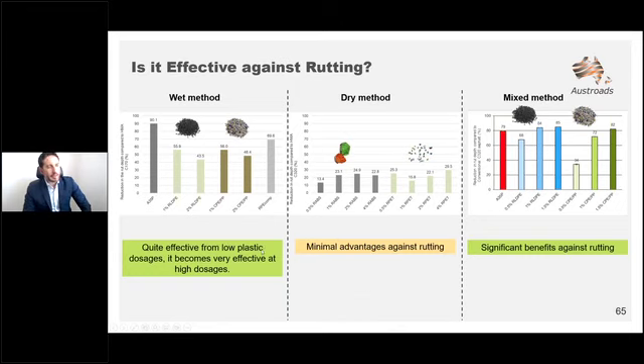Well, definitely 2 out of the 3 methods are very effective against rutting. For the wet method, even if it's a low volume of plastic that you're adding, it's quite effective from lower dosages. You can see the reduction compared to a standard hot mix asphalt mix on the left-hand side, and it becomes even more effective if you find a way to stabilize it, and therefore you can add more plastics into your binder. With the dry method, you can see that the magnitude is quite small, so there are not really great benefits in terms of rutting, not that we expected any, but I would say that minimal advantages against rutting are offered by this method.